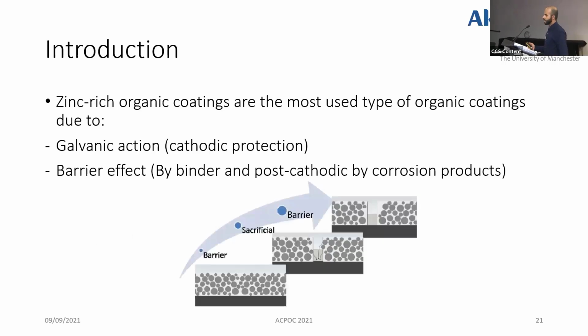So as we know, zinc-rich organic coatings are the most used type of organic coatings due to two main reasons. The first one is the galvanic action, which is offered by the zinc particles. And the second one is the barrier effect, which is offered by the binder itself at the first stage of service, and then by post-cathodic barrier protection by the corrosion products.